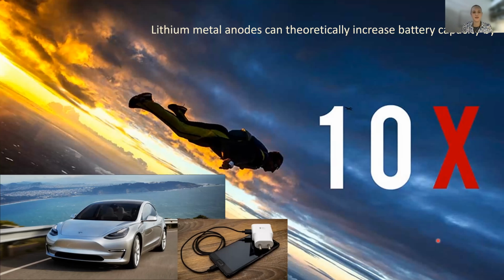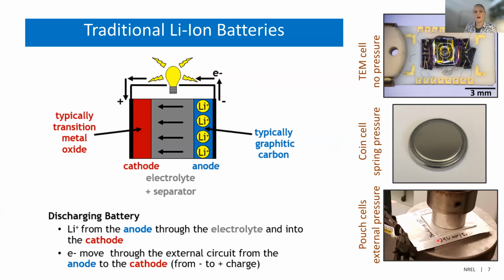So our interest was in looking at lithium metal anodes because they can increase battery capacity by 10-fold, which is very important for long life portable electronics and also for electric vehicles that need a lot of power. If you're all familiar with batteries, I don't need to go into this in detail, but of course, instead of having this graphitic carbon anode, we would like to switch that out for lithium metal so that there's no host material, and we're just electroplating and stripping lithium on the anode side. And so in a lot of our experiments, we're not actually looking at the cathode in the cell. We've been doing half cell experiments, and so we're just looking at the electrodeposition and stripping of lithium metal.